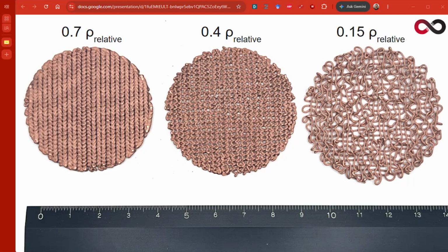Yes. And one thing that also means is that, based on this being powder metallurgy, you can somewhat tune the microstructural porosity through the sintering process, where you're actually fusing the powder into a continuous metal. But that's a global effect. Because on the mesoscale, macroscale microstructure that we're working with here, we can also control the local porosity from the coils. So we almost have two dials, one localized and one globalized, for tuning a hierarchical porosity for these materials, specifically in the metals.